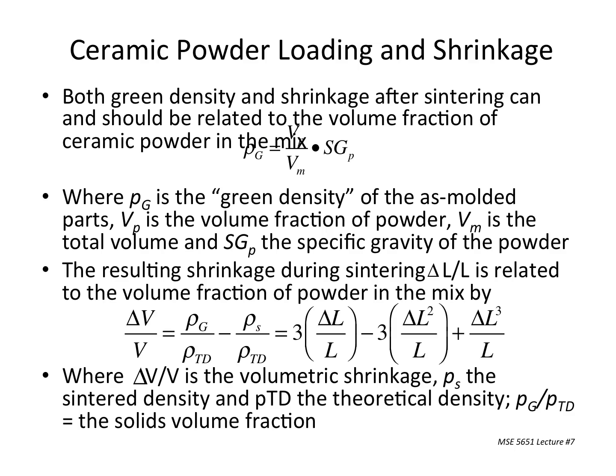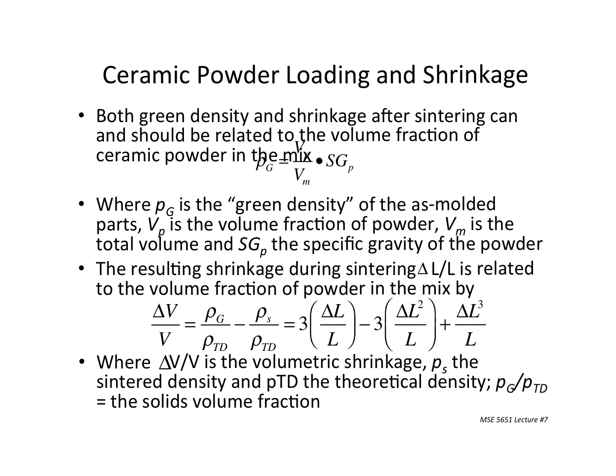Okay, so last thing I want to talk about is another issue that relates to what we're talking about here, which is the fact that we have a very high solids content, and we know we want a very high solids content because that makes our flaw sizes smaller, all right? But it does something else for us as well, and this is ceramic powder loading and shrinkage. And when I say shrinkage, I mean sintering shrinkage. So we say we shoot a part and say we really know what the heck we're doing, and it's 75% dense, right? Without being anywhere near a furnace, it's already 75% dense. And we have to, as you know, remove all that polymer that we spent so much time introducing. We now have to get rid of it.